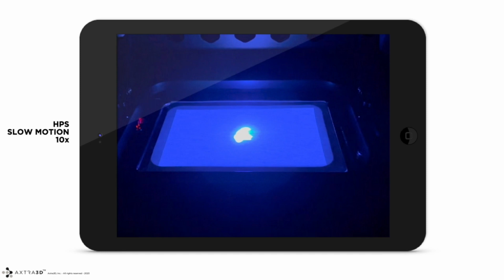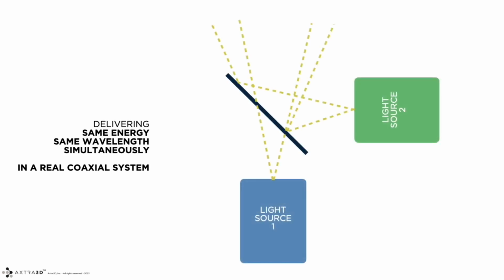So we are delivering simultaneously at the interface in a real coaxial system without, and this is extremely important, without motion of mechanical components. We are able to deliver both the light sources at the interface using a very specific behavior of the light. In our case, it is very well known today, and I'm so happy to say that our patent is now a granted patent. We are using the polarization of the light to obtain what we are calling HPS technology.